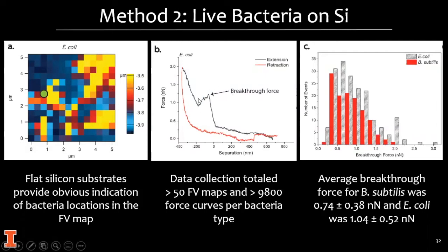So we're measuring the breakthrough force, and what I want to point out now is that this data looks a lot noisier than the data I showed you before. That's because as you begin piercing all these bacteria, eventually the tip will become cross-contaminated from these samples. It's just the nature of this type of experiment. We're purposely breaking apart the membrane, so there's nothing we can do. It just becomes part of your sample variation here, and that's another reason why you should be taking a lot of these measurements.